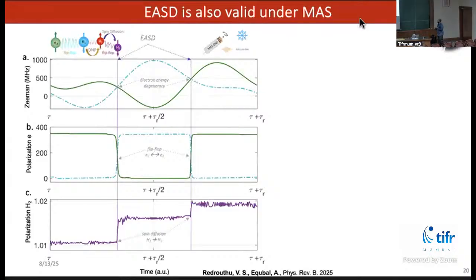I'll not go into details, but this spin diffusion picture is actually valid even for magic angle spinning. When we physically rotate the sample, because of anisotropy, these electron spins have anisotropy, so the energy levels oscillate periodically. And there will be scenarios where two energy levels are almost degenerate. So there would be level crossing. And what we can see here is every time there is a level crossing between two electrons, they flip-flop. And the flip-flop of two electrons also causes a nuclear spin flip-flop, which is indicated as a rise in the polarization of the nuclear spin.